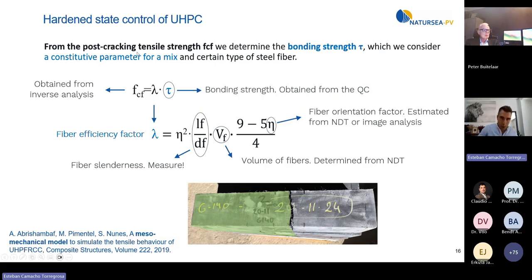Okay, what do we do with the post-cracking tensile strength? With this value, we obtain the bonding strength, tau. The bonding strength is how much the steel fiber bonds to the concrete. This is what we consider the constitutive parameter for the mix. In the lower left corner, you can see a published document where you can find much more information about this mesomechanical model. It was developed by Abrishambaf, who I have seen is now in the audience. So thank you, because your procedure has been very useful.